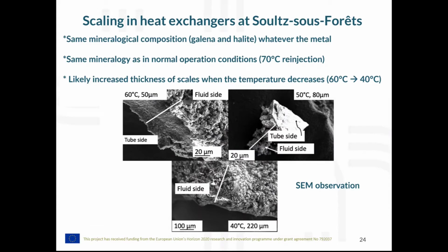So if we look at the different metals on which the scales deposited, in fact, we find exactly the same mineralogical composition made of galena and halite, whatever the metal. We see the same mineralogy in the lower temperature tested exchanger as in normal operation conditions when the reinjection is made at 70 degrees centigrade temperature.